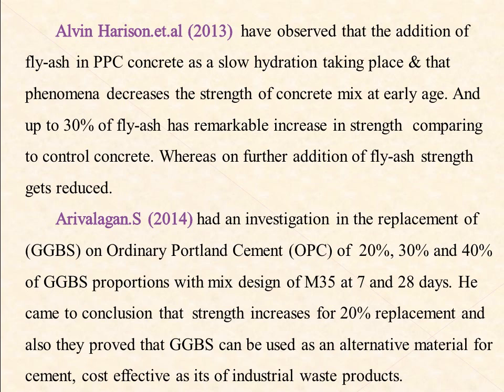The first paper was by Alvin Harrison. He observed that the addition of fly ash in PPC concrete has a slow hydration taking place, and that phenomenon decreases the strength of the concrete mix at early age. Up to 30% of fly ash gives a remarkable increase in strength compared to controlled concrete, whereas beyond that, with more addition of fly ash, strength gets reduced.